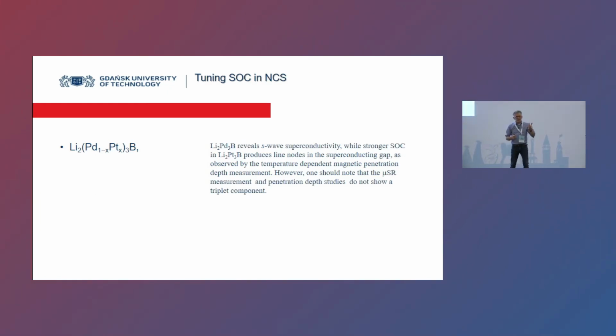Actually, there are only 2 models or systems in which you can tune spin-orbit coupling. This is the first one, and this is the oldest one: lithium 2, palladium 1 minus X, platinum X 3, boron. So replacing palladium by platinum, you just make the spin-orbit coupling stronger, and we hope, or they hope, that this spin-orbit coupling will introduce the spin triplet superconductivity. There is some controversy, but I am not going into details.